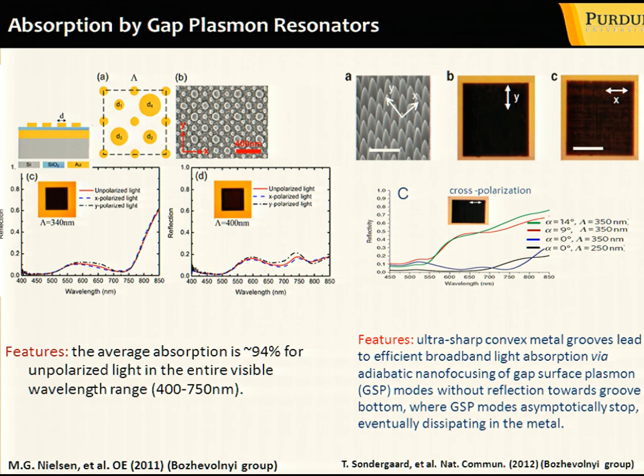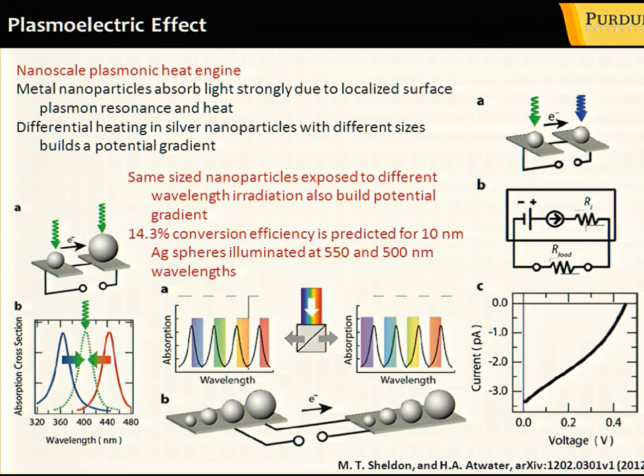Yet another structure, they use these ultra-sharp convex metallic grooves, V-shaped grooves. And in this case, a very interesting phenomenon occurs: gap surface plasmons adiabatically propagate through this structure, slow down, eventually stop, and at that point get absorbed. So in this case, they also accomplished very strong absorption in an extremely broad spectral range for polarized light. And that's, of course, as I said, a key element to improve photovoltaic elements: to have absorption in a broad spectral range and at all angles of incidence and all polarizations.